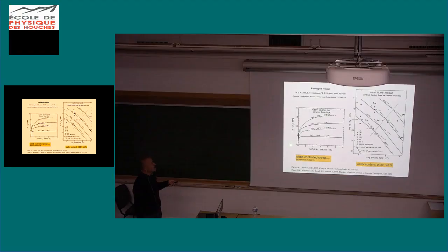Another very large part of the work was done by Neville Carter and his co-workers, who deformed Avery Island salt to quite high strains at 10 to the minus 9 strain rate. So just imagine how long this experiment has taken. And they have also found that there is a kind of climb-controlled creep. The exact mechanism wasn't so clear.